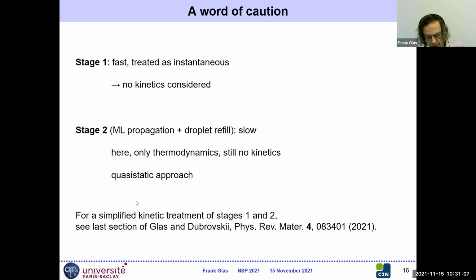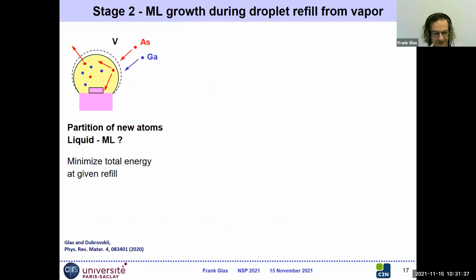So it's a kind of quasi-static approach where the system can adapt at any time to its lowest energy state. Of course, we should do a kinetic treatment. For a simplified kinetic treatment, simplified meaning that we did not consider all the features, such as the non-monotonous decrease of the step energy, but we treated stages 1 and 2 kinetically, I refer you to the last section of the paper I published with Professor Dubrovskii. No, it's not 2021, it's 2020. It's a fruit of COVID.